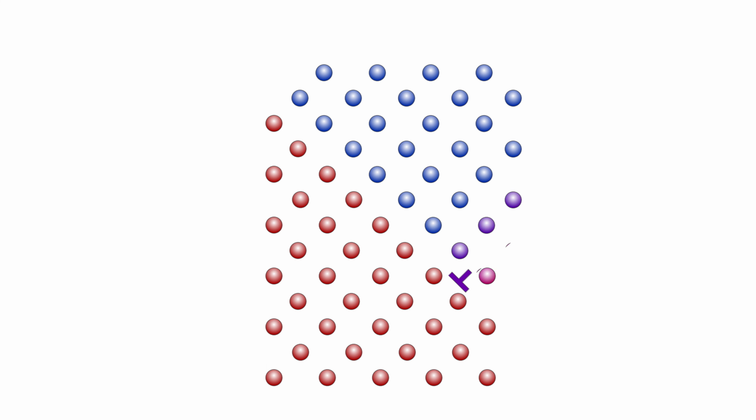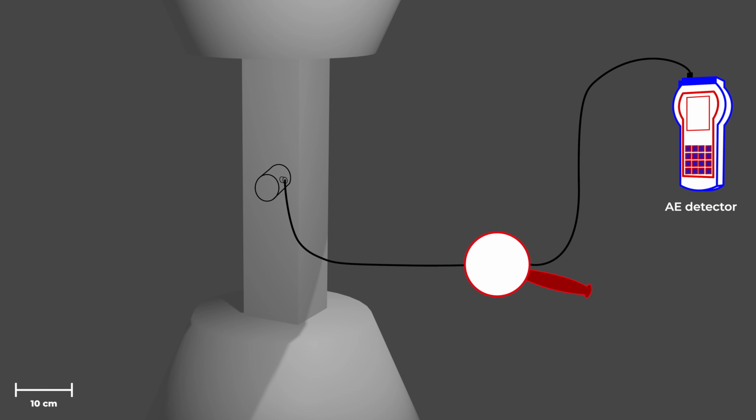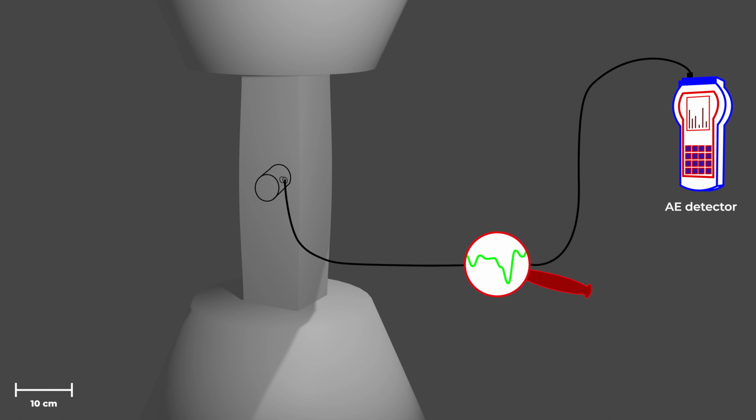deformation of bulk metallic materials usually appears as a smooth process, both in space and time. This is seen in the so-called deformation curve, showing how much stress is necessary to achieve a certain level of deformation. During the deformation, the collective movement of dislocations causes emission of ultrasonic acoustic waves. Now, you can hear an example of such an emission transformed into the audible frequency range.